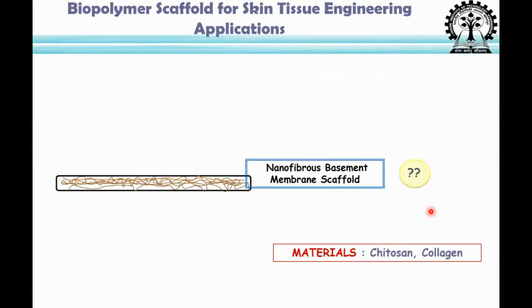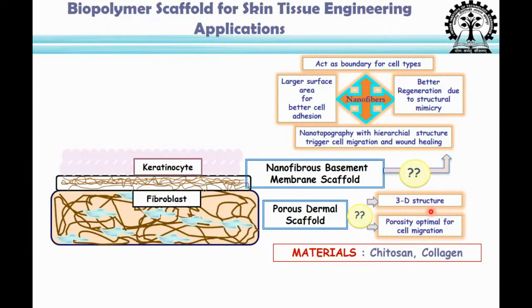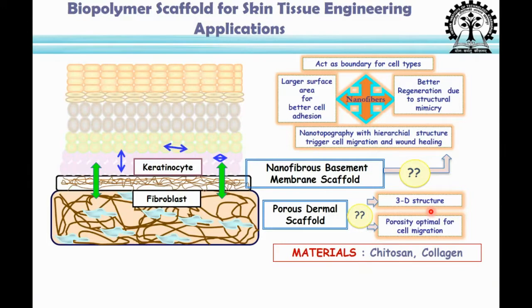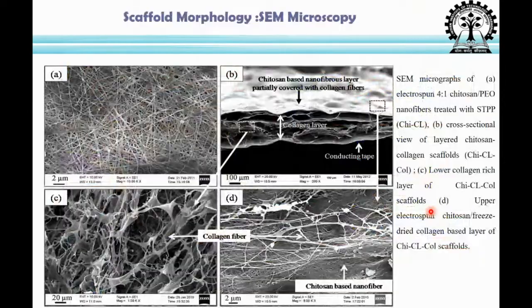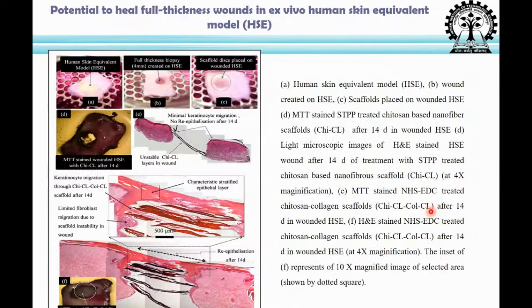Similarly, in wound dressing, we have a lot of activities. As you know, the skin is a bilayered or maybe multi-layered structure. There is a fibroblast, connective tissue, and there is an epidermal layer. And in between, there is a basement membrane. So if you can make a device where fibroblast and keratinocyte are compartmentalized, yet they can interact, and this in-between layer can be antimicrobial and can inhibit bacterial and microbial invasion, then you can make a better device. With this idea in mind, we have used electrospinning as a method, using an electrospun membrane, and we have infiltrated collagen. On the top of the electrospun membrane we have grown the keratinocyte, and on the bottom side we have grown the fibroblast. And we have done testing with a skin equivalent model.